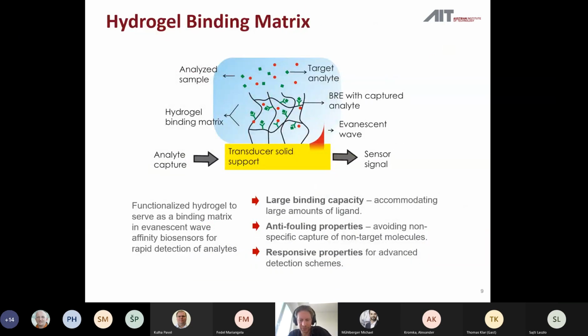Another aspect I would like to raise attention to is how one treats the surface of these metallic structures. In affinity biosensors, one typically modifies the surface of these optically active structures with molecules which can specifically capture target analyte from the liquid you analyze at the surface, and then efficiently optically probe it. And this can be done by, for instance, polymer-based architectures, based on a thin hydrogel film with cross-linked polymer networks, which can be infiltrated with a large amount of these bioactive capture molecules.